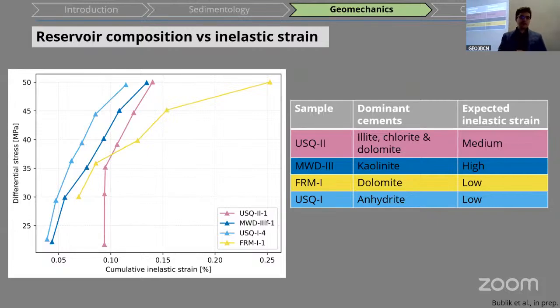So you can see here, cumulative inelastic strain. So that's how much compaction do we observe in these samples against the different differential stresses. And what you can see here is that we have light blue, which is a sample where we expected low, so that's good. Then we have blue and pinkish, where we say, okay, medium and high. So they're changed in the order, but generally what we expect, they're higher than light blue.